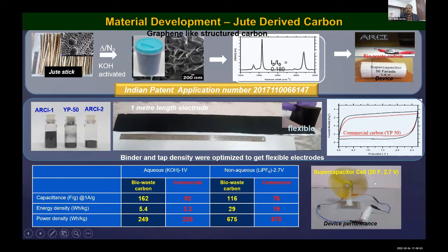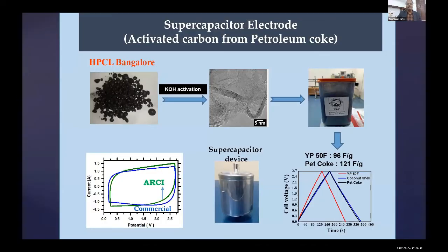But that's not enough. If you want an electric vehicle to use a supercap, it should be more than 1000 farads. So we were looking at whether we could do that. We have a good beginning, but the jute stick carbon has only 20% yield. When you take 1 kg, you get only 20% of that converted to carbon. So that's not enough. In the meantime, HPCL has listened to us, and they understood that we have the capability of scaling up the materials and designing the scientific part of the material suitable for supercap.